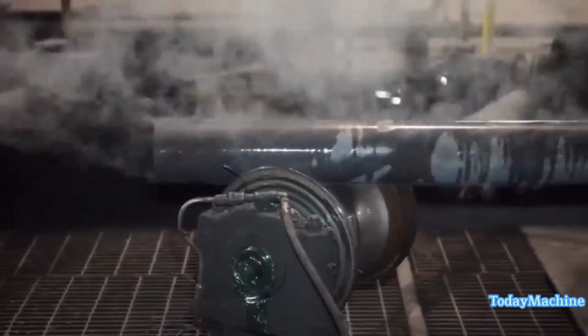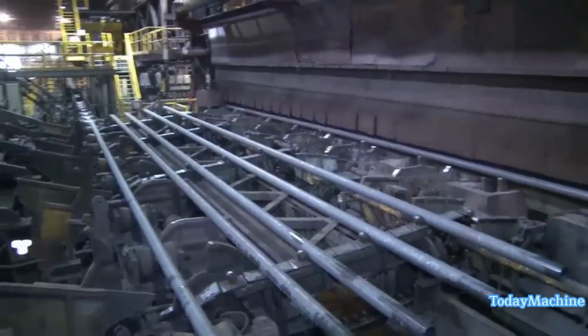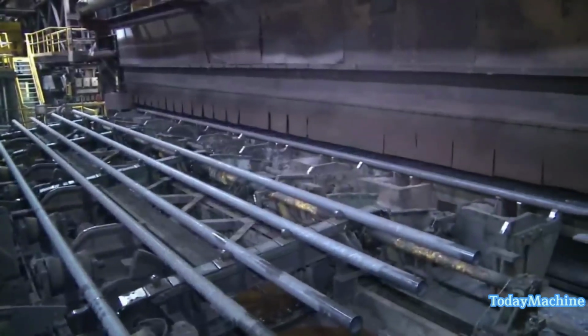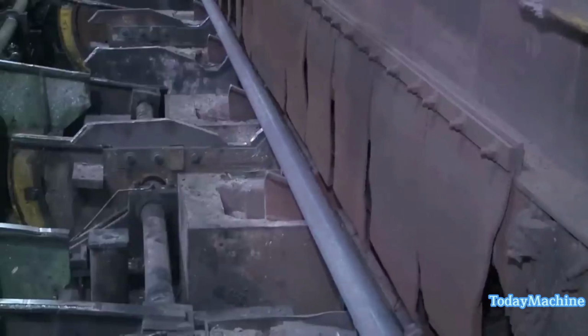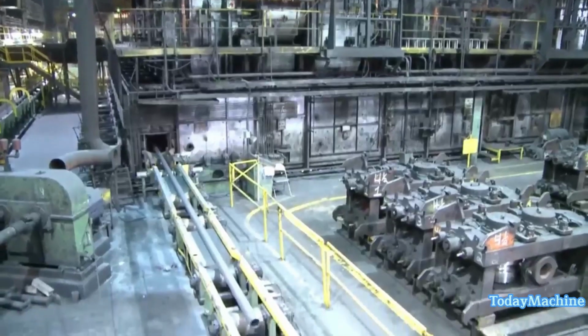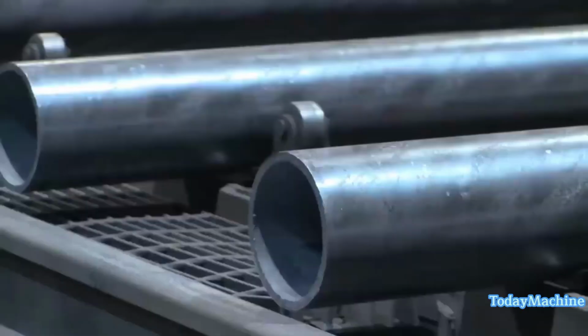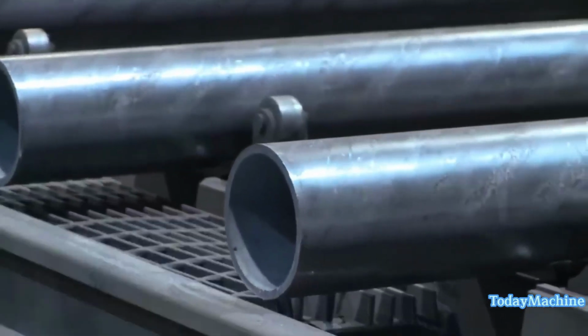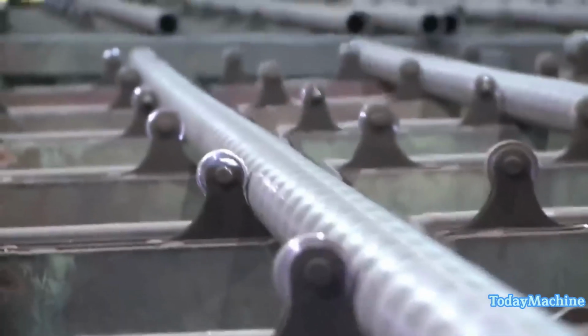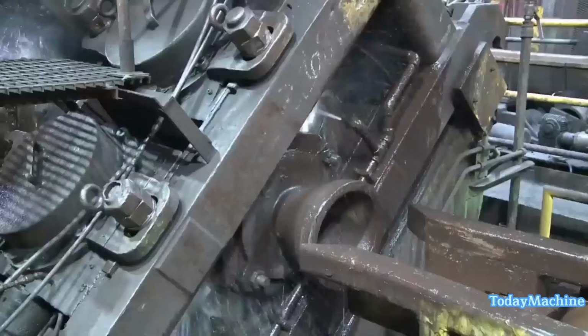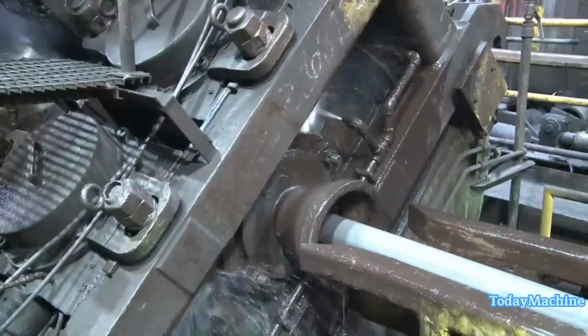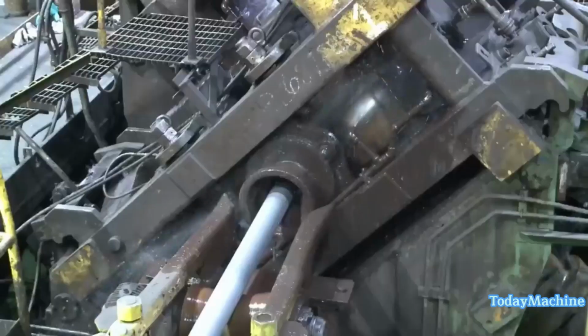Next, the pipe is transferred to a tempering furnace where it is preheated to 510 degrees Celsius and slowly cooled. This tempering process increases the pipe's ductility or toughness. Precise control of time and temperature during tempering is critical to achieving well-balanced mechanical properties in the finished pipe.